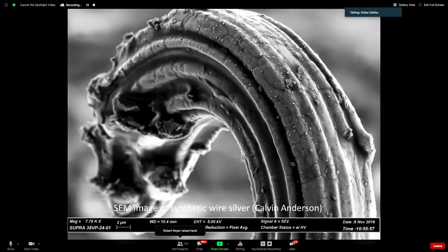And so another question related to the silver grains was about the orientation. Do they have a random orientation, or are they oriented crystallographically? So we've looked at a number of samples. There's a much more thorough study on the internal texture of these things by a technique called EBSD, and that was done by Thomas Bollinghaus and others in Germany. I'd have to refer back to their paper to look at exactly their findings. But in general, you don't have a very strong preferred orientation. There might be a small preferred orientation, but for the most part, it's relatively random.